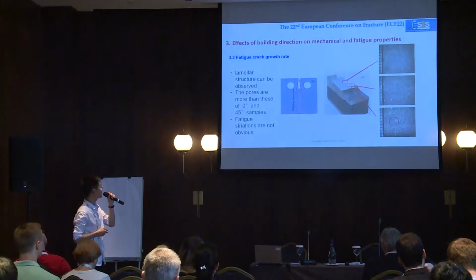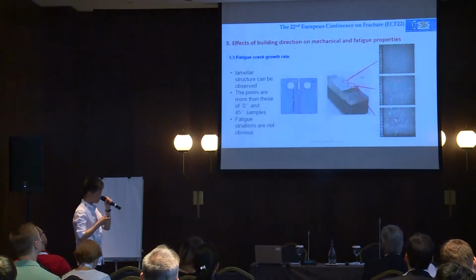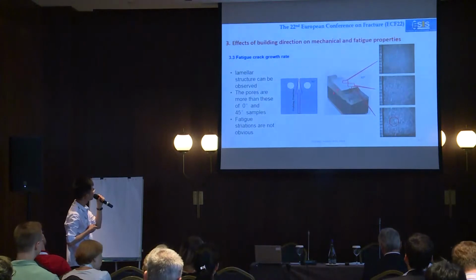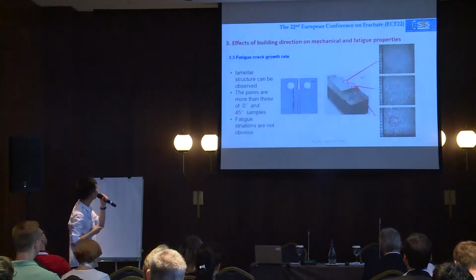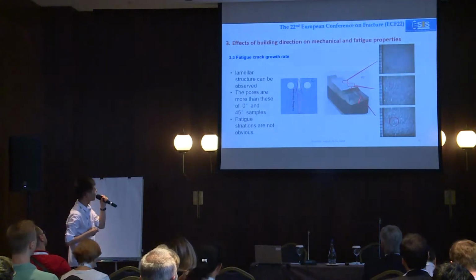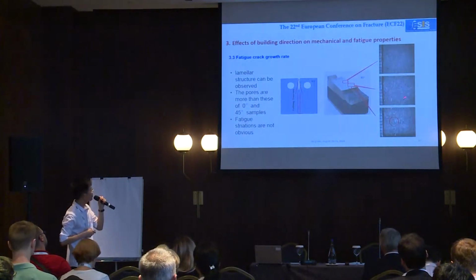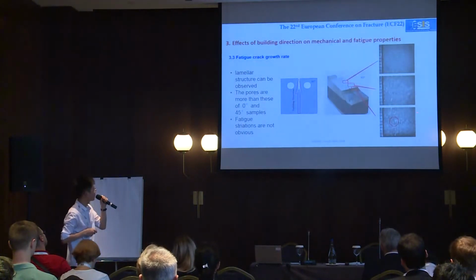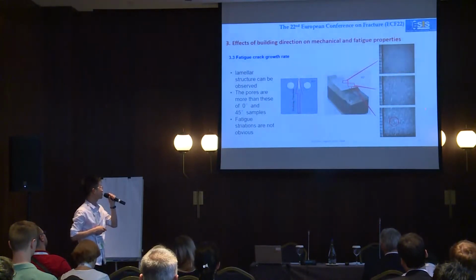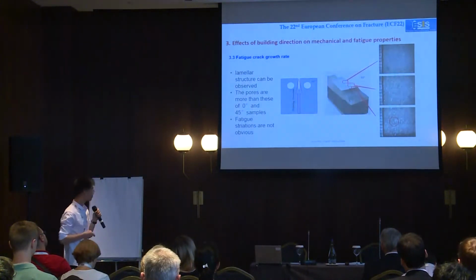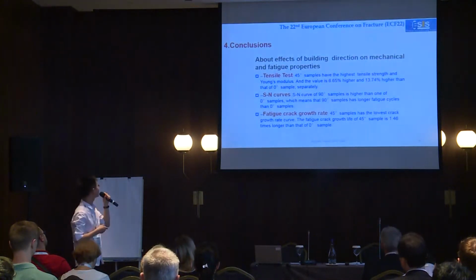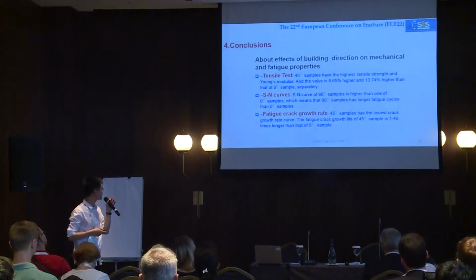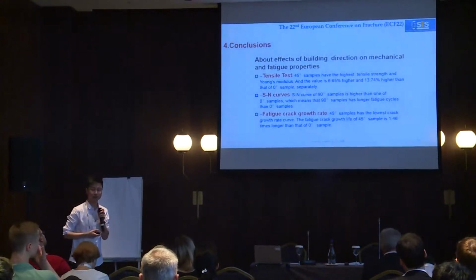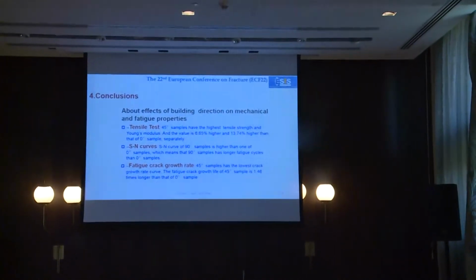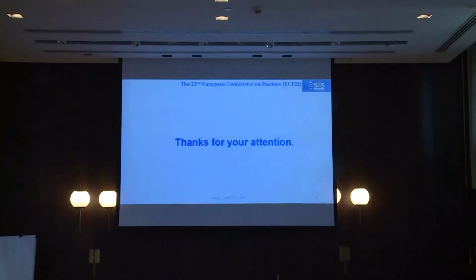This is the fracture surface of 90-degree samples. Laminar structures can be observed in this, just like this. And in the microscopes, the fracture surface is really messy, and the pores are more than those of 0-degree samples and 45-degree samples. That's some conclusions. Okay, that's the work we have done, and there is still some work ongoing. Thanks for your attention.